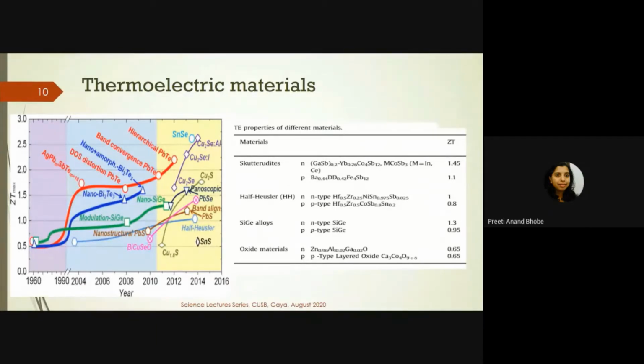Like you can see here half Heuslers, PbSe, copper selenides and copper sulfides, and many kinds of things. But interestingly, there were also silicon germanium alloys and skutterudites and oxides and various other materials that were known. Interestingly, in 2014, there was a material that crossed all these boundaries along the y-axis. If you see, the highest numbers are coming around a material shown here in blue, which is SnSe, the tin selenide material. It basically crossed all the boundaries and showed the highest ZT known to us till date.